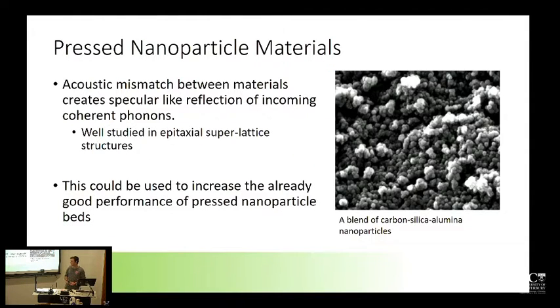There was actually a precedent for this in literature, and we were following along with a lot of what they had studied. The idea was that we had silica, alumina, and also carbon black. Those are three different materials which have really strongly mismatched mechanical properties, and hopefully we could start to get an increase in thermal insulating performance.